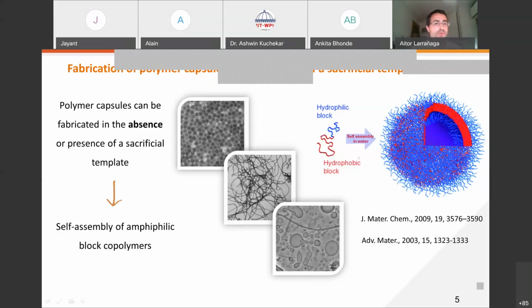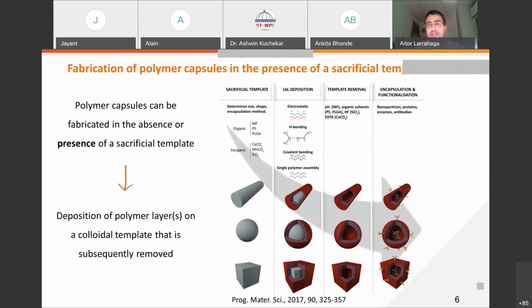Well, in the case we want to fabricate polymer capsules in the presence of a sacrificial template, here the concept is completely different. In this case, the process relies on the deposition of a single polymer layer or multiple polymer layers on a colloidal template that is subsequently removed, leaving behind a hollow polymer capsule. As a sacrificial template, as you can see in that picture, we can use virtually any kind of colloidal template, either organic or inorganic, with different shapes and also different sizes.